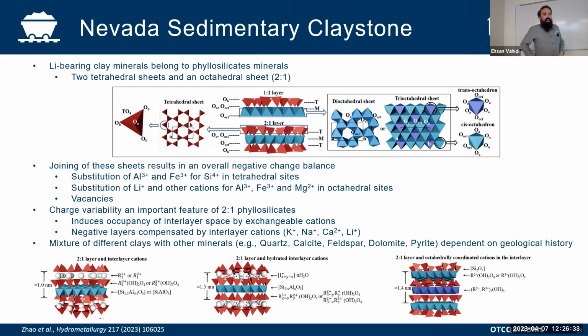And these clays found in Nevada are basically phyllosilicate minerals of alternating layers of tetrahedral and octahedral sheets. Depending upon the order of these, 2-1 layer, 1-1 layer, or combinations and permutations thereof, will dictate the overall charge on this mineral. Joining of these sheets results in a negative charge balance, and substitution of various elements in various sites, then balancing it with other cations, contributes to this large negative charge on these clay particles.